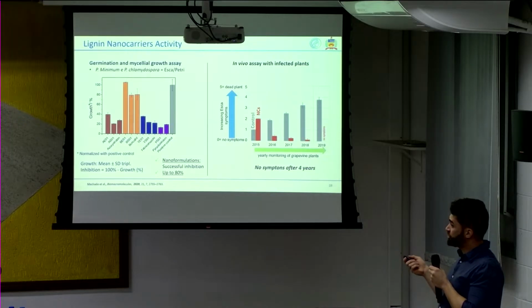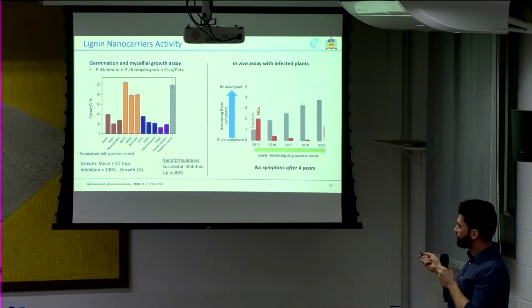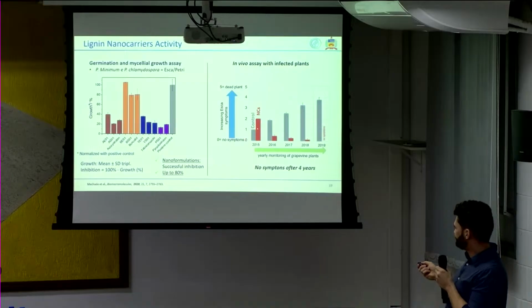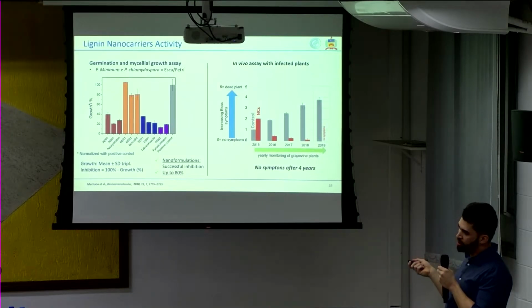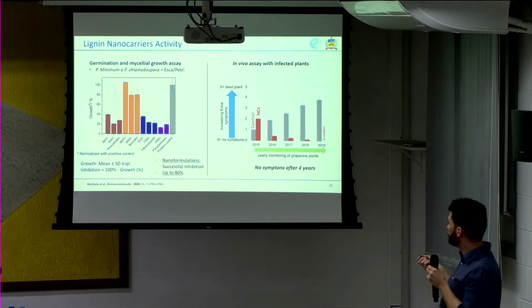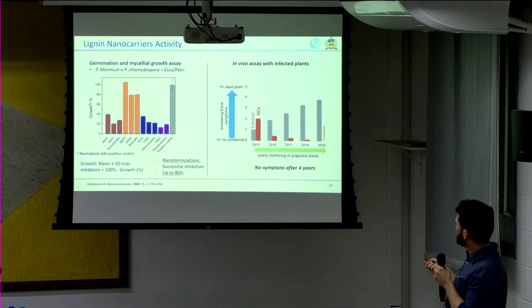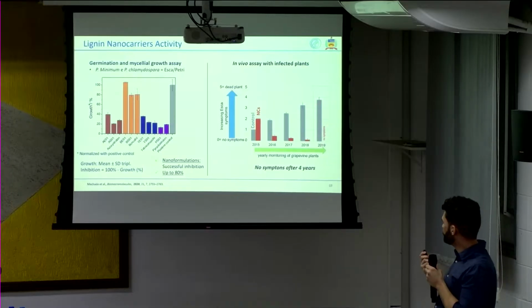So we thought maybe we should do a different study because let's see if it works in vivo as well. So we did a study in vivo for 4 years, more or less, and we did a score for the symptoms of the disease. 0 means no symptoms, 5 is a dead plant, and in the beginning we have the control that's not treated and the plants treated with the nanocarriers, and they are only treated once, so the nanocarriers are injected in the trunk only once, and after 4 years the control got sicker and the plants treated with the nanocarriers were healed, fully healed, no symptoms at all.